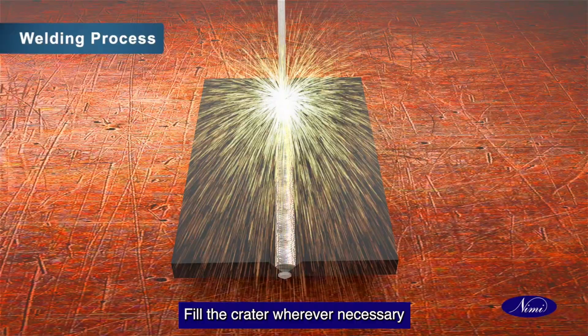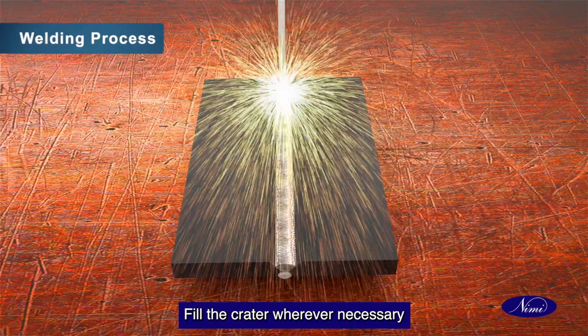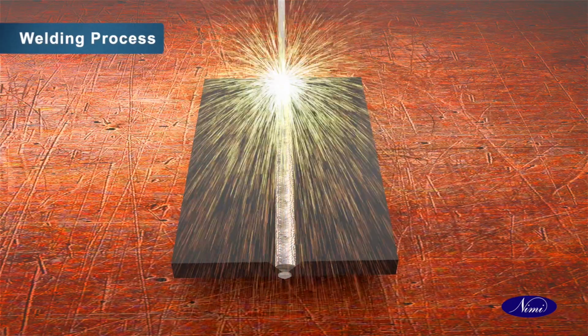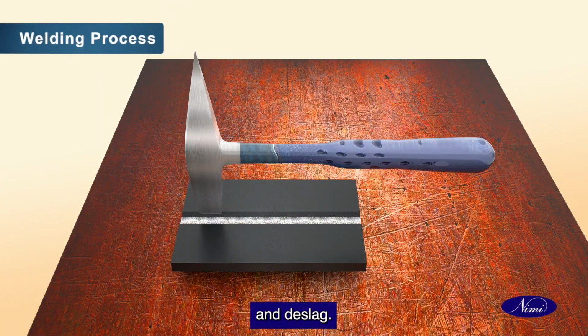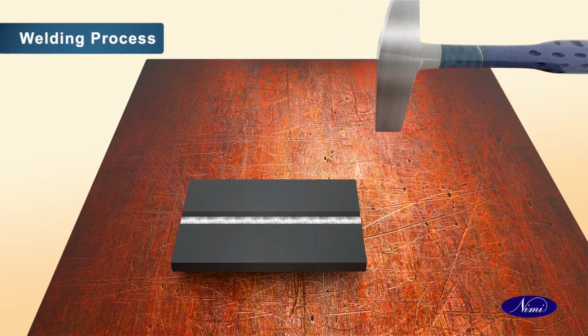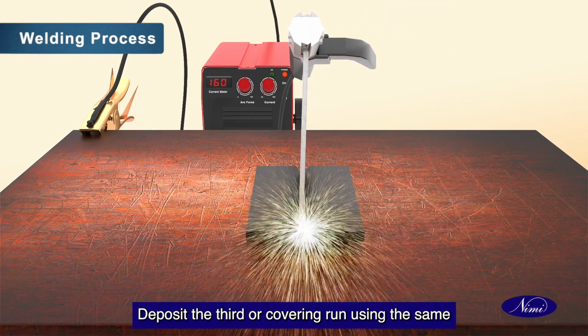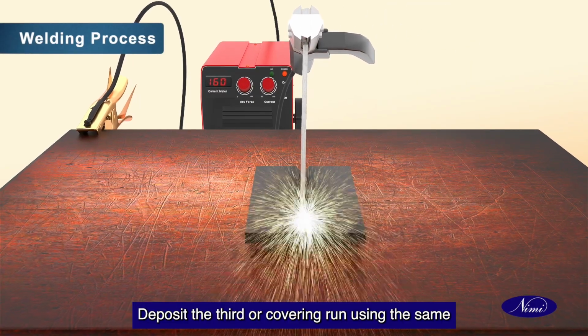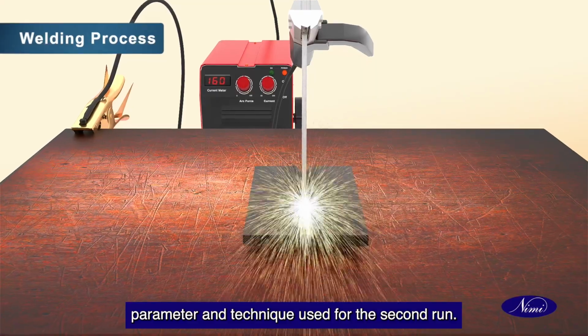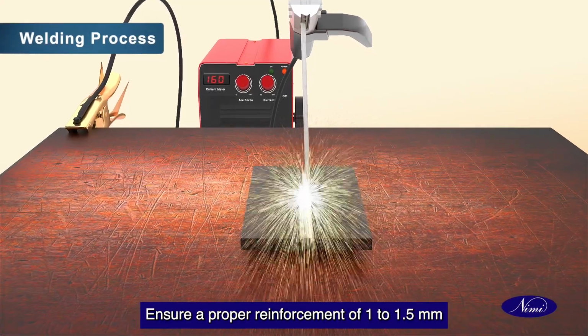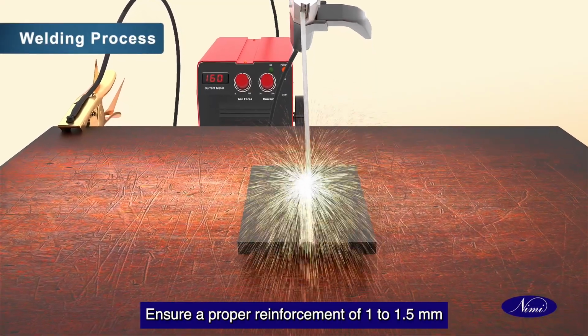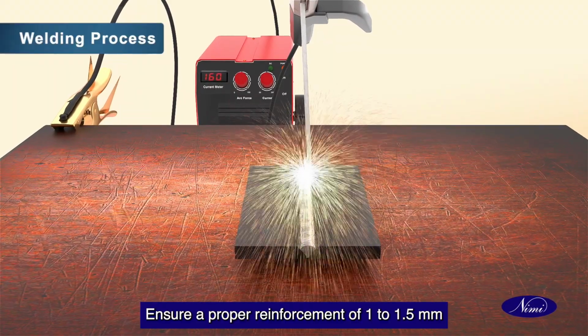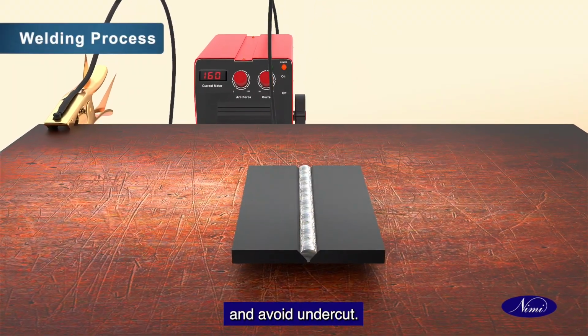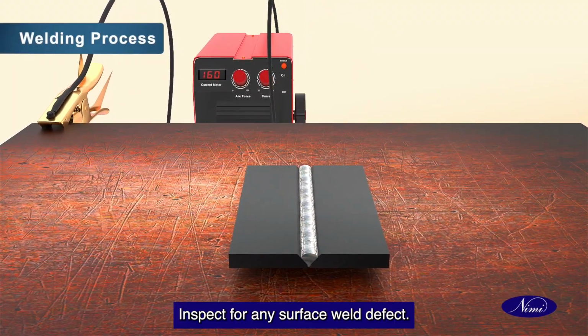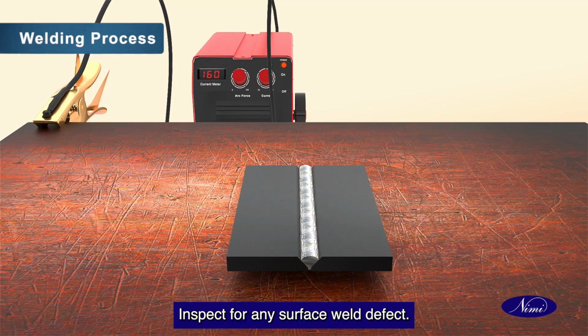Fill the crater wherever necessary and deslag. Deposit the third or covering run using the same parameter and technique used for the second run. Ensure a proper reinforcement of 1 to 1.5 mm and avoid undercut. Inspect for any surface weld defect.